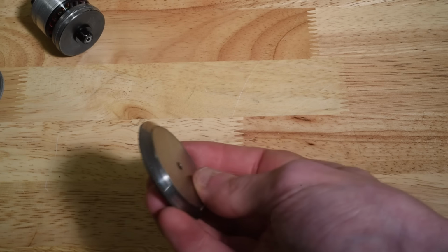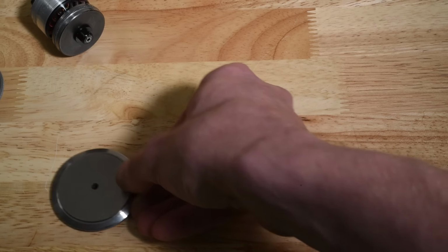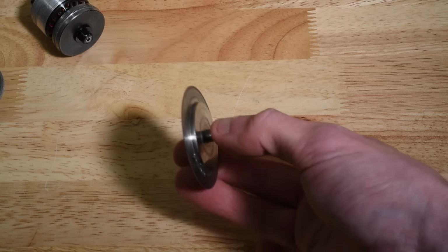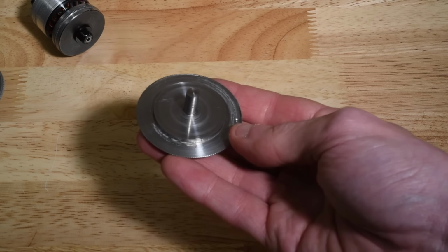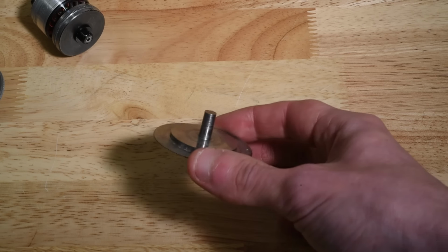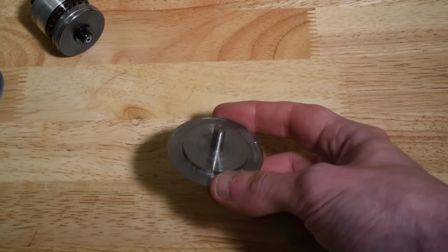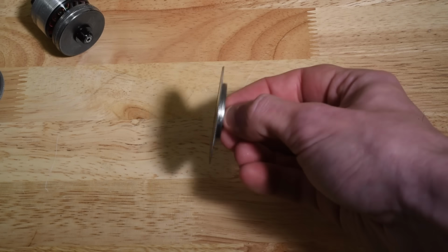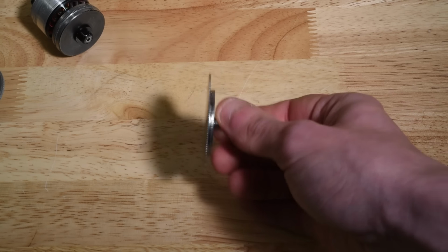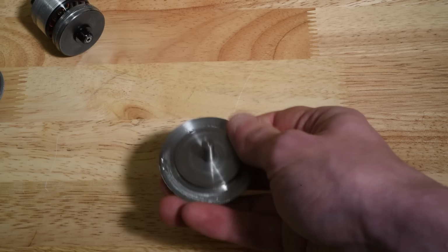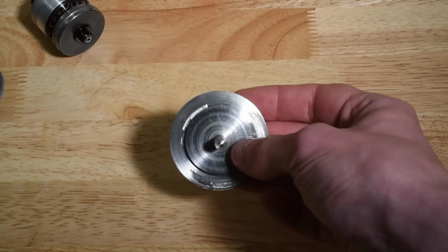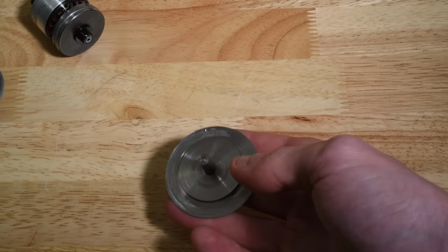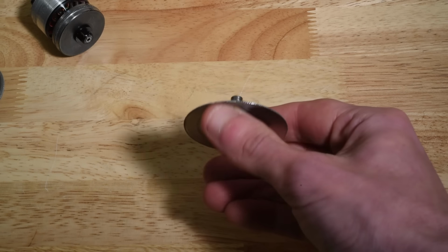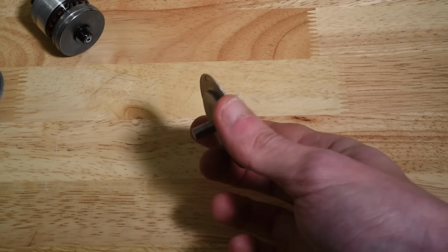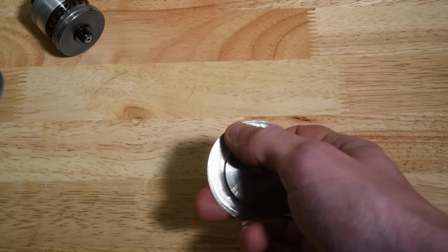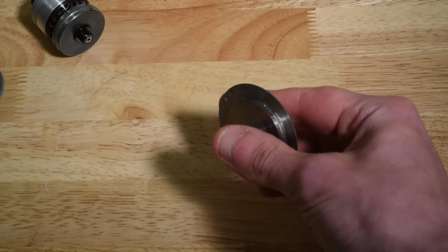And making our own that were thin enough, meaningfully thinner anyways than the ones that PCBWay would make, well, it was possible, but it turned out to be really difficult. And we made the mistake of thinking, aha! We'll use the same rod stock and turn down 90% of it to make a 6mm shaft that's short and will be stiff so we won't have any camber or wobble. Fools that we were. Turns out that it's just hard to turn this much material away. It takes forever, and it tends to break tools, and man, you're fighting work hardening the whole time, and inevitably you end up bending or deflecting the thin edge you're trying to make, and once you've bent it, well, you can't really bend it back and keep it balanced.